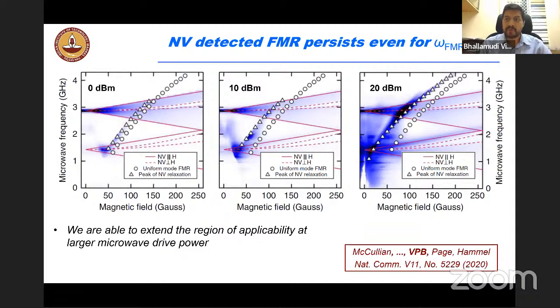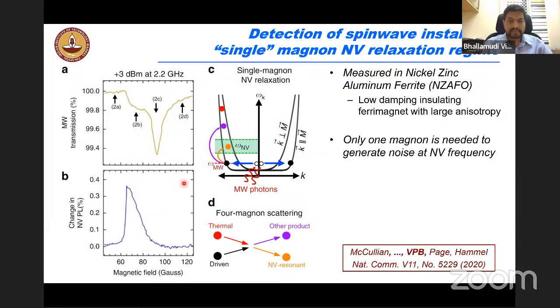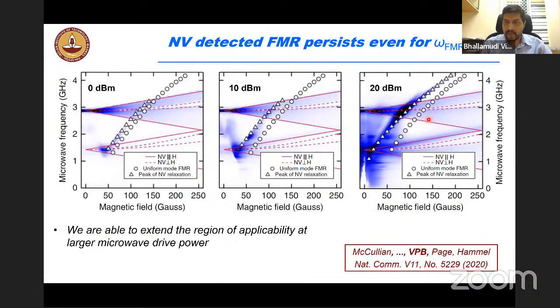But as it turned out, when we did these measurements at higher powers of microwave, we see that this region where we could do the detection is being extended. And so this again, we thought we should understand. And the way again, what we can see is that there are two effects happening. One is that the peak where the NV response is not quite at the uniform mode at higher powers. You can see that it slowly moves away from the uniform mode FMR. And the other is the extending of the range here.